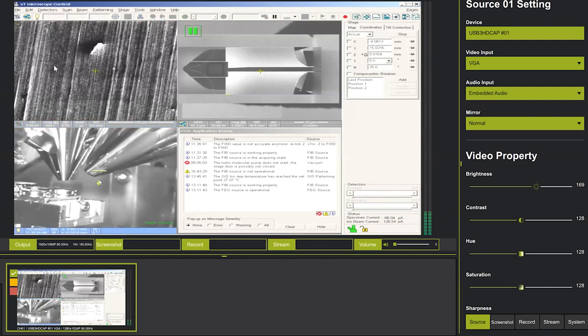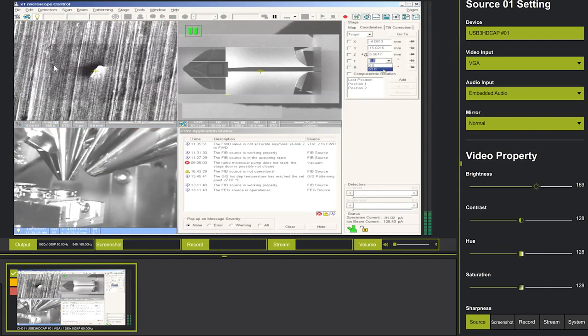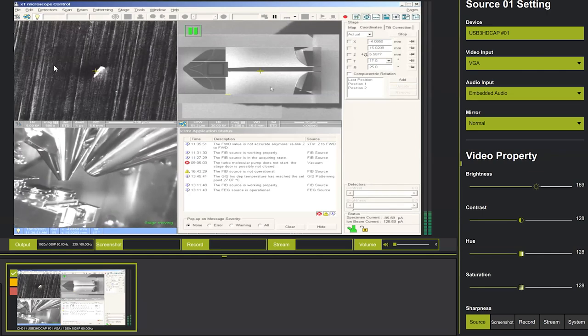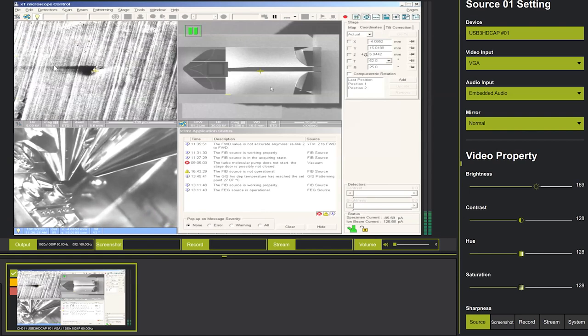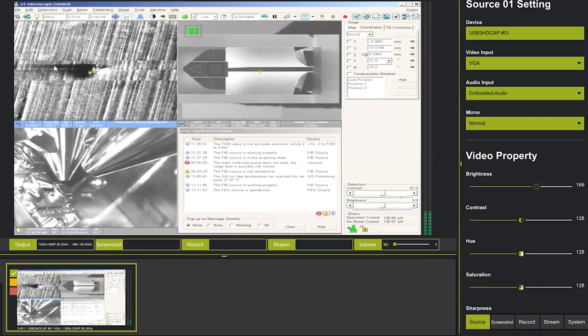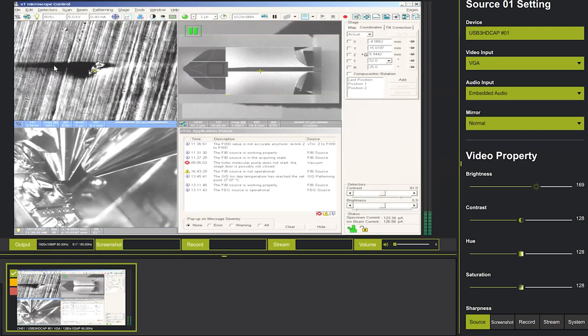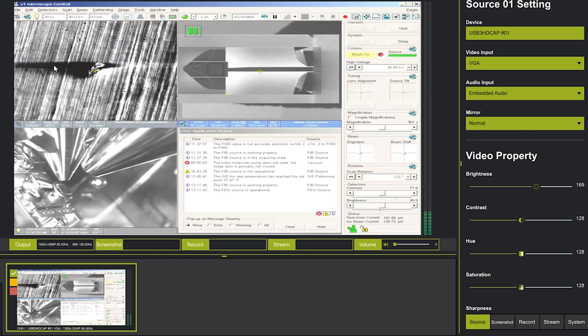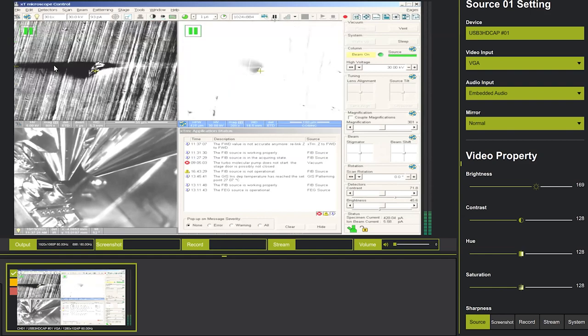So I'm looking at a dust particle on the copper surface. While the tilt angle is changing, the electron beam is still hitting the same particle. Okay, so now because of the geometry of this instrument, the ion beam is hitting perpendicular to the sample surface. Is the ion beam ready? Yes, the ion beam is ready. For the ion beam condition, I use 30 kV, 93 picoamp for navigation purposes. Let's see if we can get the image here.